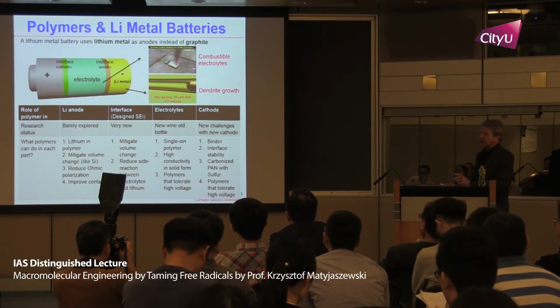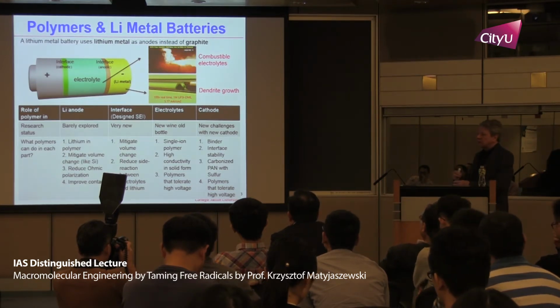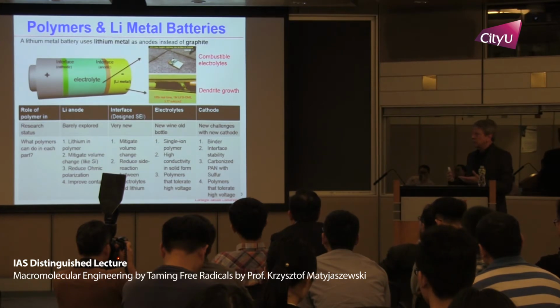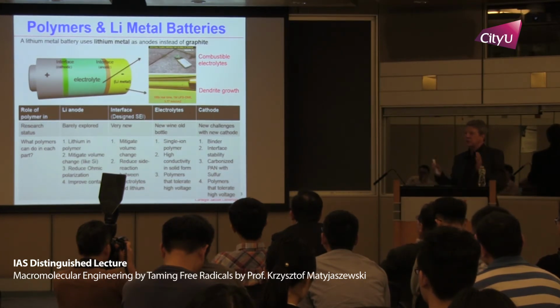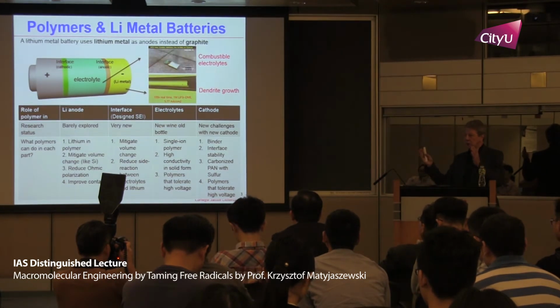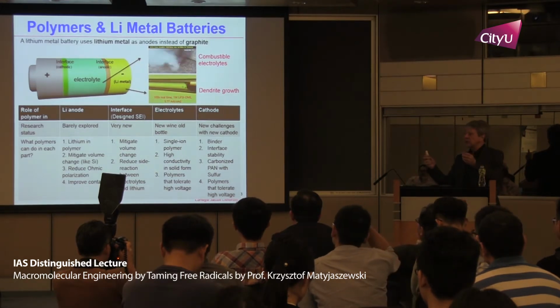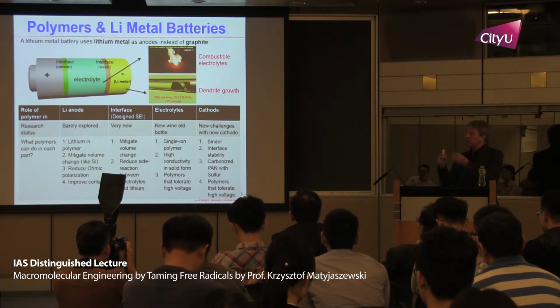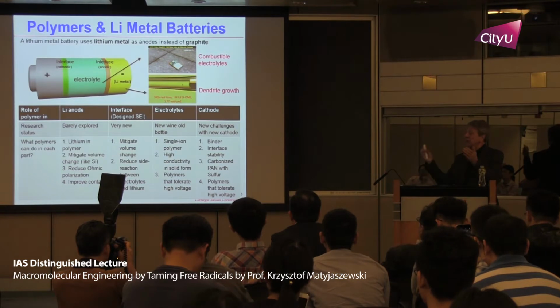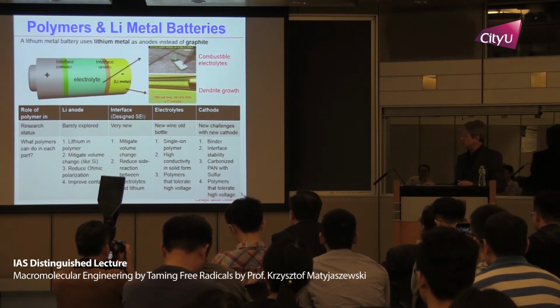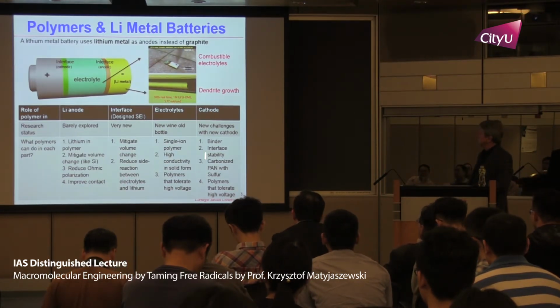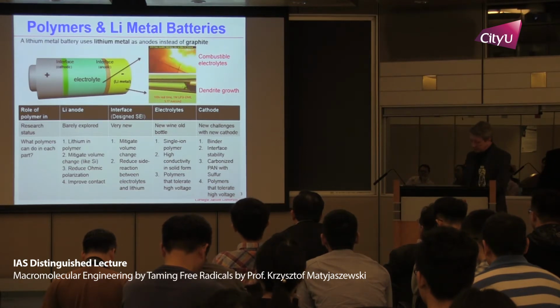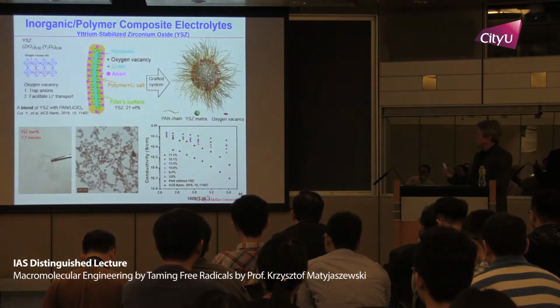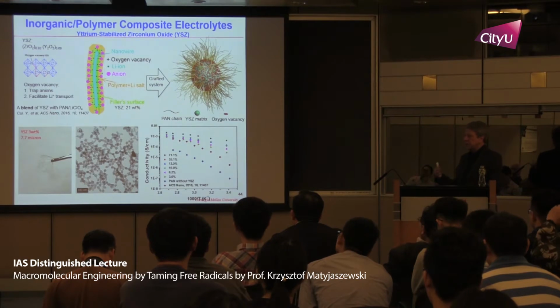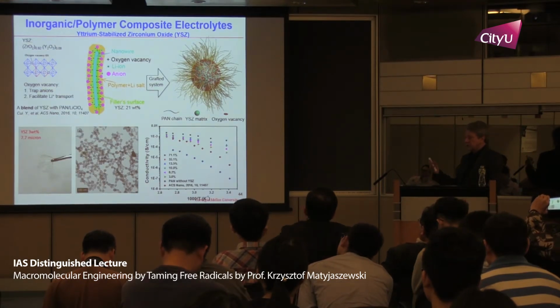Electrolytes are of very critical importance. And one example, and I will show you this example, is totally reversing the solid electrodes, cathode and anodes, and the liquid electrolytes, making solid electrolytes and liquid, for example, anodes. And then the same story is with the cathodes. So here's what happens if you start replacing liquid electrolyte with a solid.